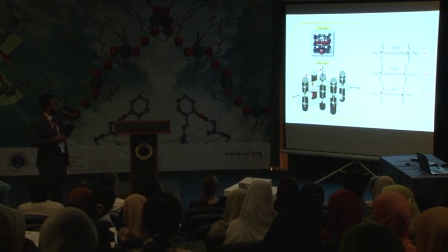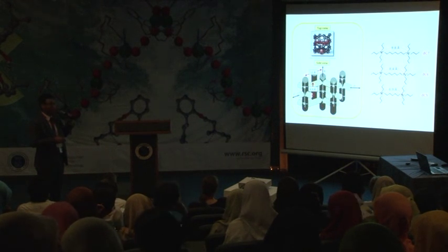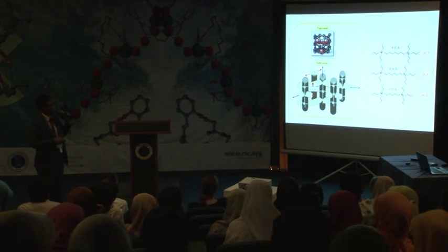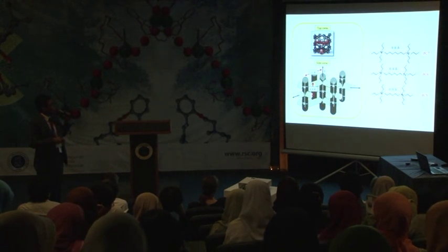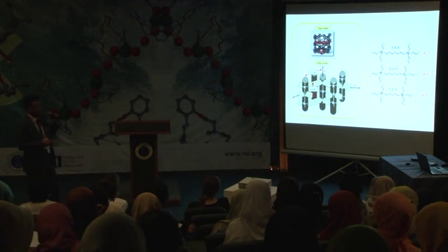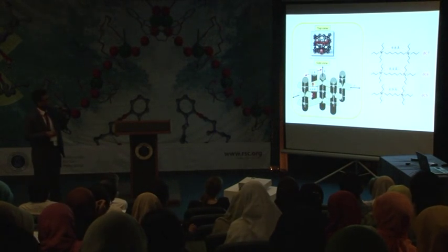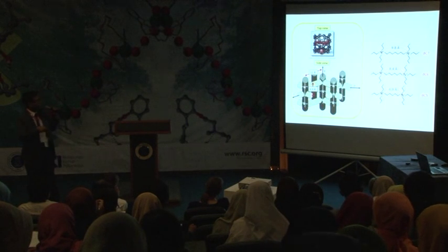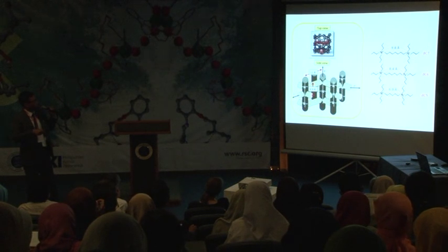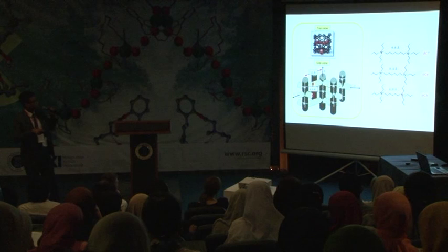So normally MFI zeolite was constructed by only a single ammonium ion, here the tetrapropyl ammonium ion. But we can have diammonium, in fact. But we have to negotiate with the chain space between the two ammonium ions. If you have 7 carbon chains, probably it's 9.8 angstrom. Yeah, probably it will fit into this channel. If you decrease to 8.4 angstroms, I don't know if it works, but you can decrease again down to a 5 carbon chain.